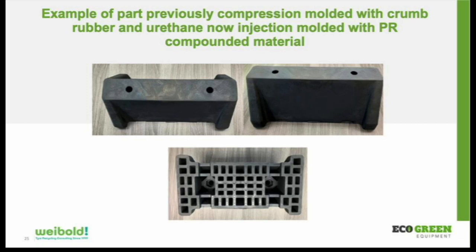You can see on the back where we've cored out. What's hard to see in these photos is they were also able to put the logo of the company onto the part. And not only did it reduce the weight of the part, but it also increased the break point by nearly twice as much, so up to 10,000 psi before this part broke.